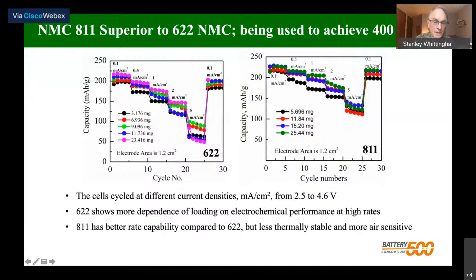Also, for high energy density, we need very high loading. So we show here from 3 milligrams per square centimeter in the cathode to 23. There's quite a difference in here. And to show this is kinetic, we go back to the original conditions and it's back to normal. You now see in the 811 there's much less of a fall off. So the 811 can tolerate a higher current density. It also can tolerate higher rates, and the amount of loading has less impact. So our